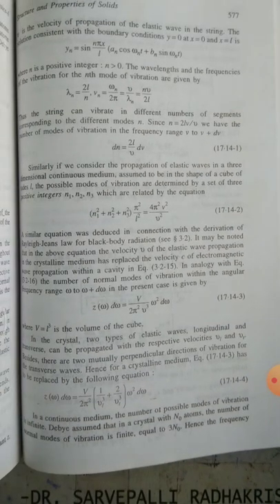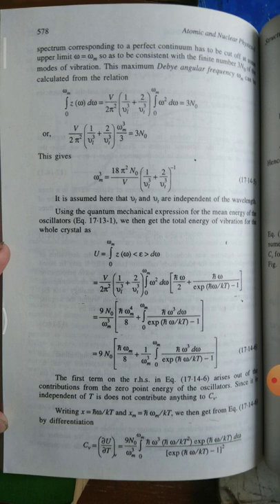Next, in a continuous medium the number of possible modes of vibration is infinite. Debye assumed that in a crystal with N₀ atoms, the number of normal modes of vibration is finite, equal to 3N₀. Hence the frequency spectrum corresponding to a perfectly continuous medium has to be cut off at some upper limit ω = ω_m, so as to be consistent with the finite number 3N₀ of modes of vibration.